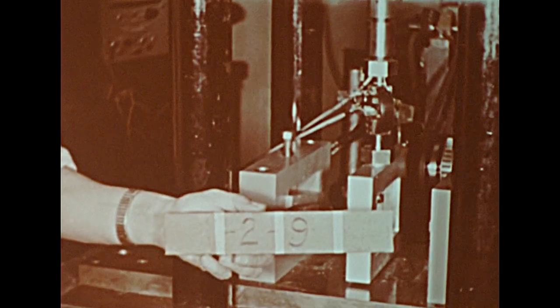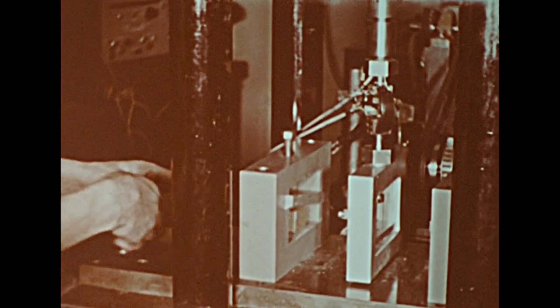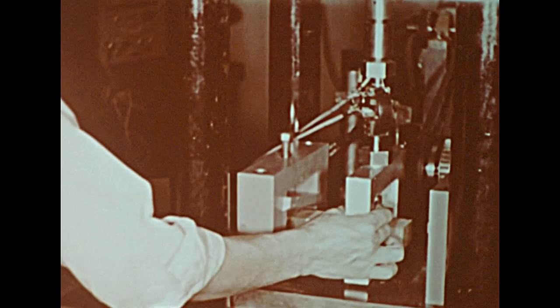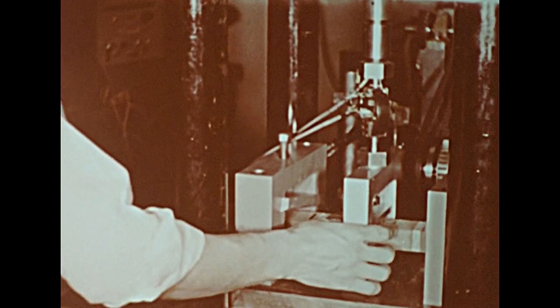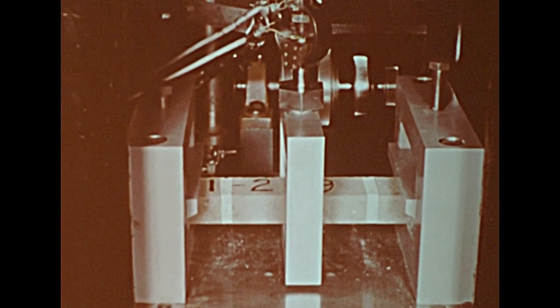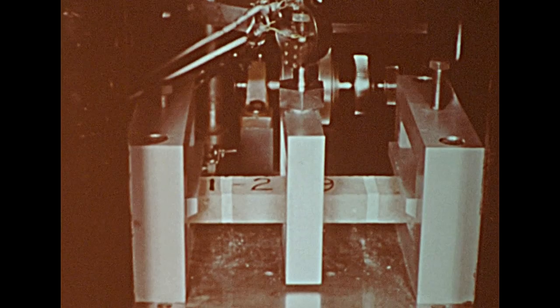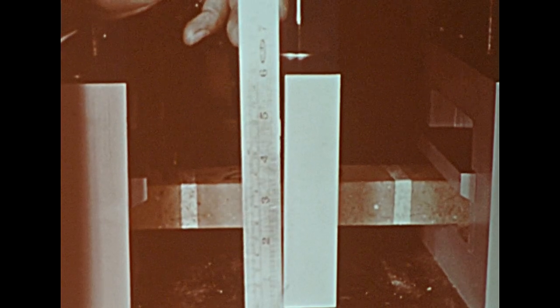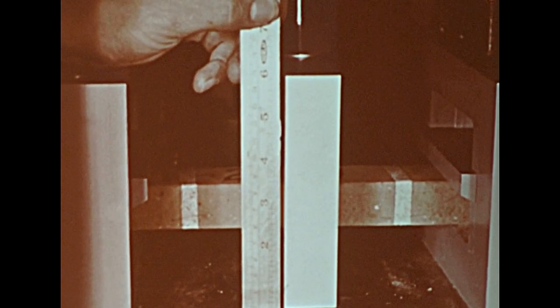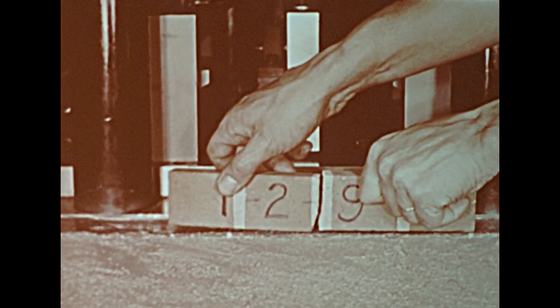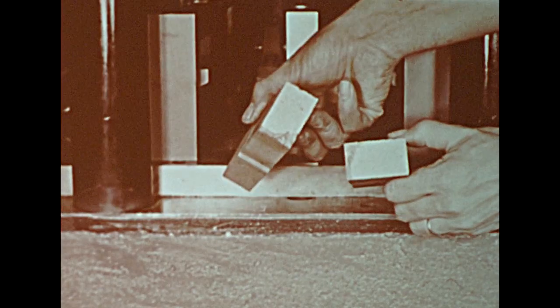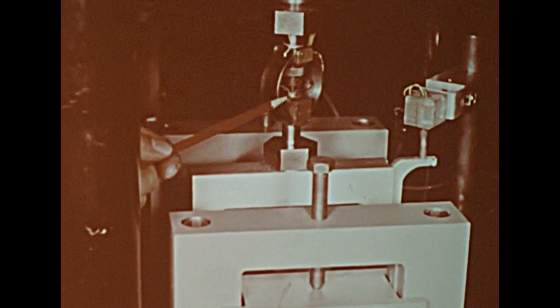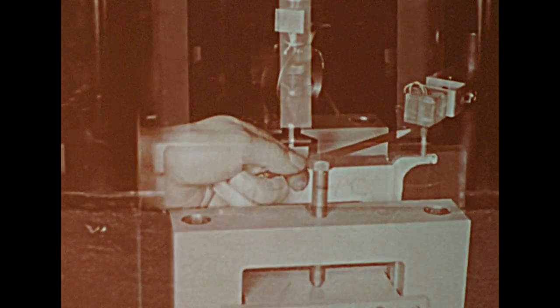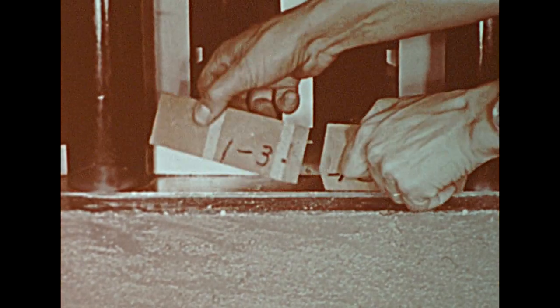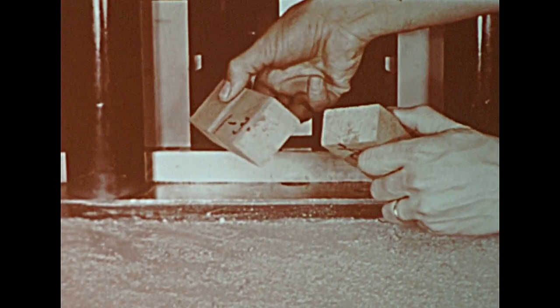Bars of bricks whose mortar joints had been aged for 3 months were clamped in a horizontal position for testing. The objective of the tests was to determine the amount of elasticity in lime mortars and their ability to withstand stresses. When stresses were relieved before the bars broke, they tended to move back to their original position, indicating elasticity in the mortar joints. When stresses were continued to the breaking point, the high lime mortar joints invariably broke through the joint itself. On the other hand, in similar tests made with low lime mortar joints, there was not only little joint elasticity, but when the bars broke, the joint separated cleanly from the brick, showing less positive bond.